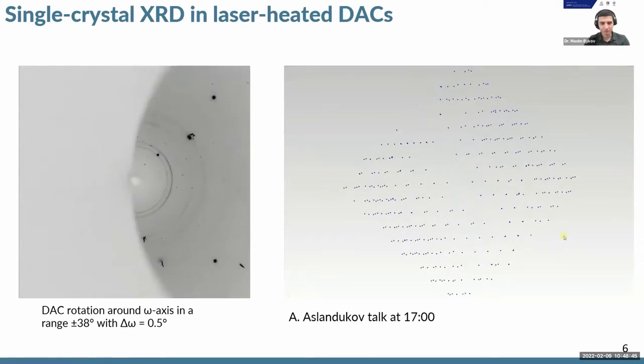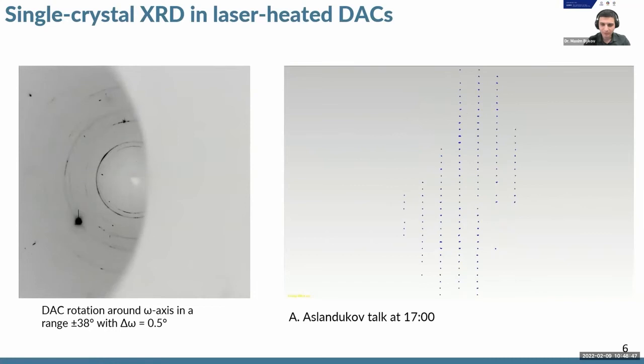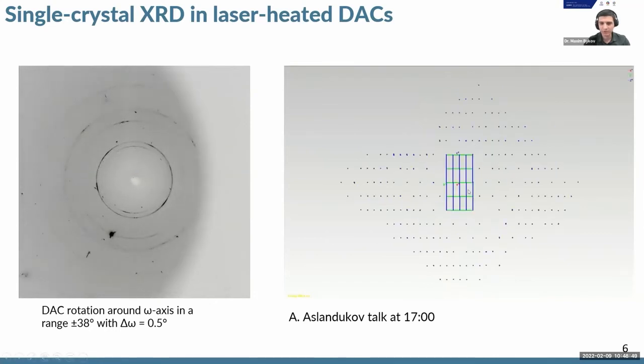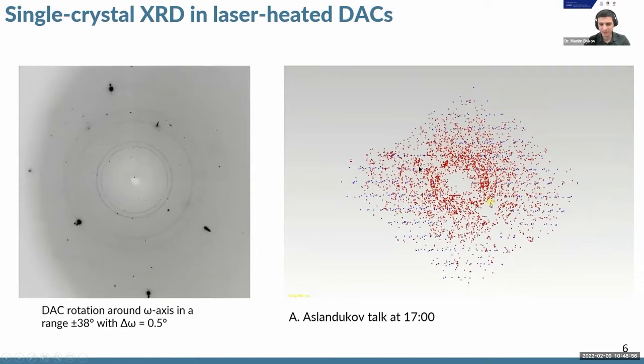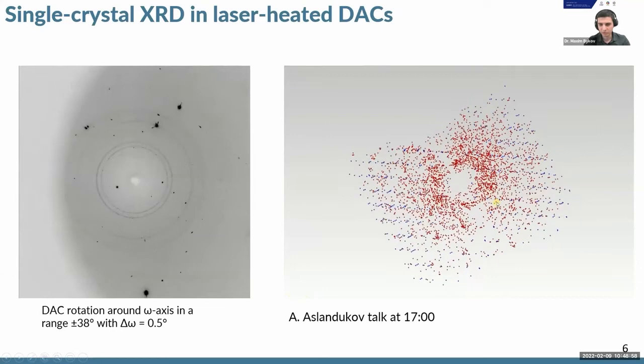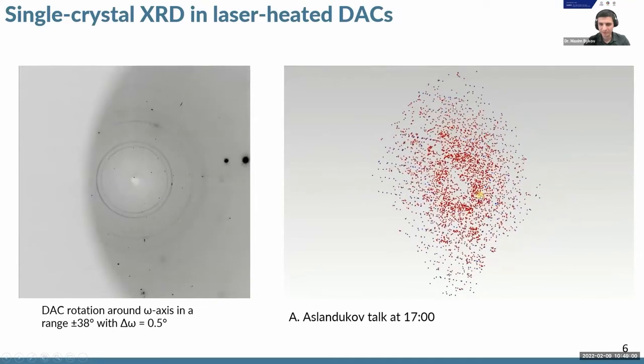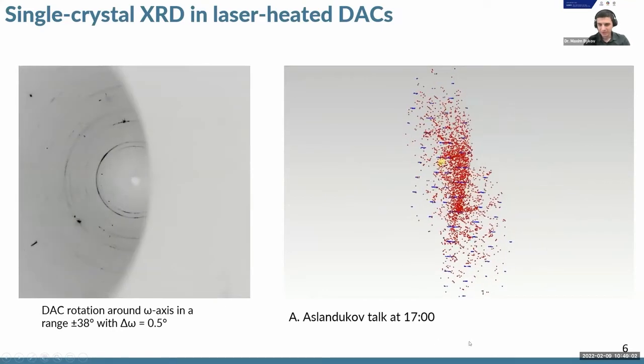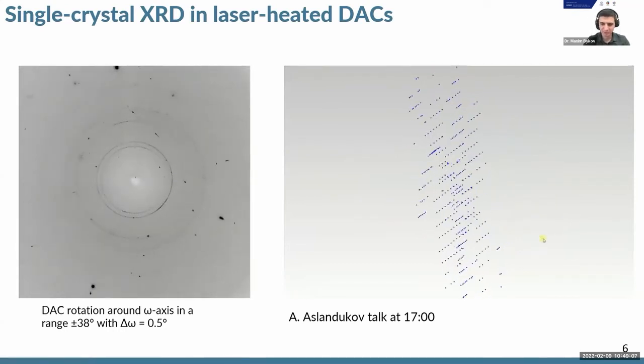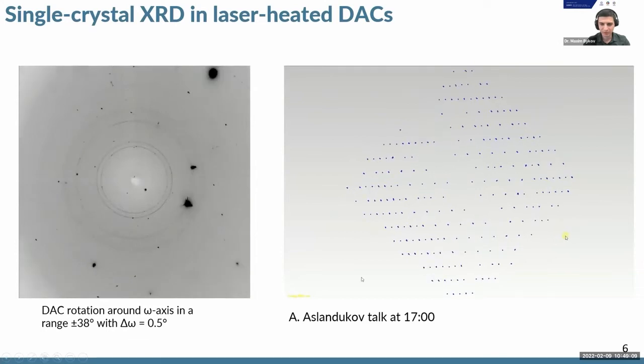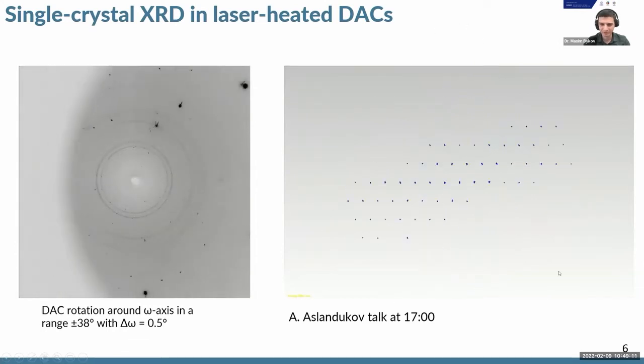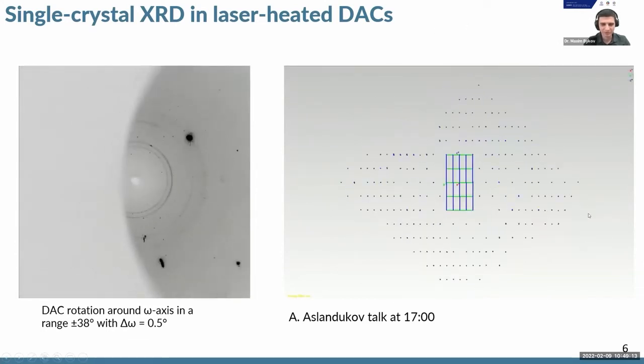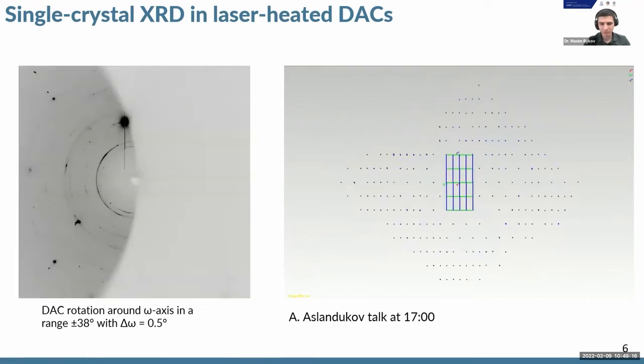This allows us to reconstruct the peak search table in 3D, and then an experimenter would manually select the lattice of usually one of the strongest diffracting grains from this cloud of peaks. And actually, when we started this kind of crystallography, this was the most difficult part to enter this field, because it really depends on the patience and the qualifications of the experimenter.